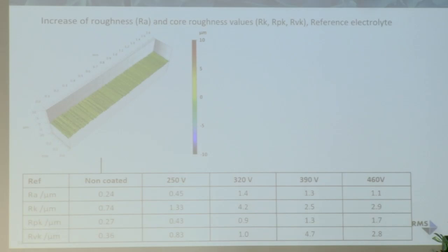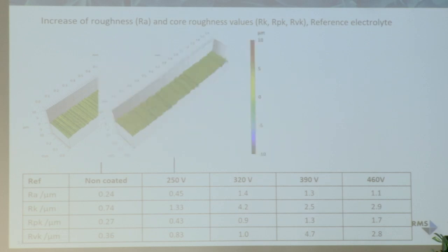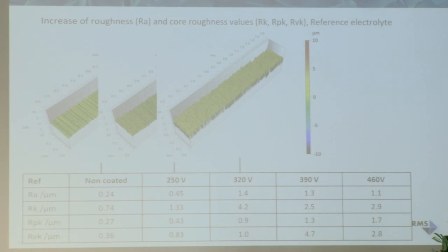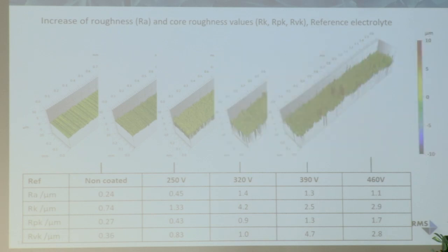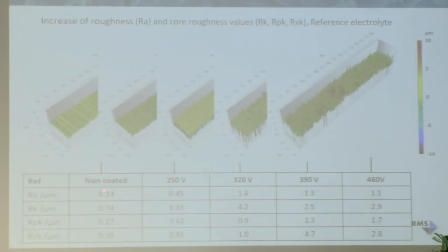We looked at the coatings. We tried to characterize them first by surface topography. This is the topography of the plate without coating, you see still the machining traces. If we have a thin coating, the machining traces are still there. But the thicker we go with the coating, the rougher it gets. So sorry, that was too quick. So you see Ra values are rising from 0.2 to about 1.43. Those are core roughness parameters. There are many more parameters, but I only show these.